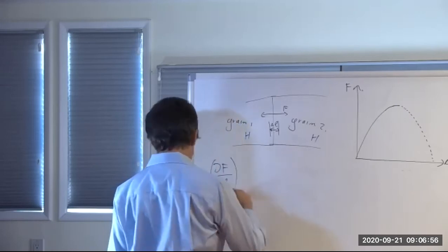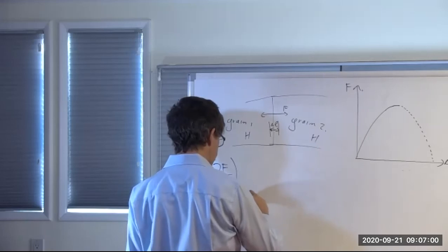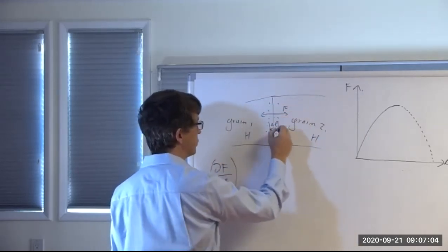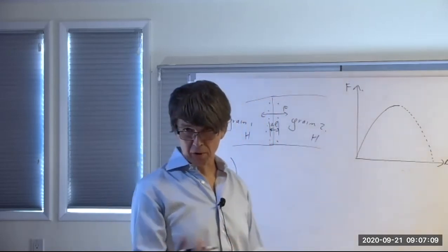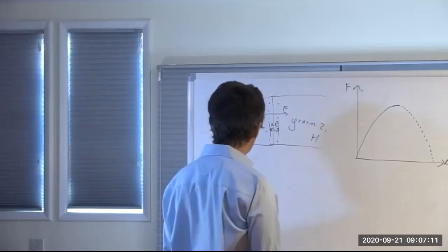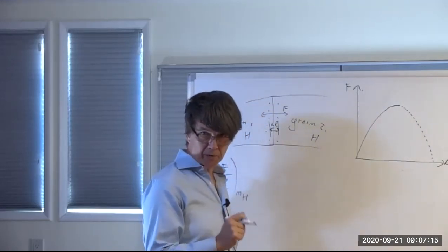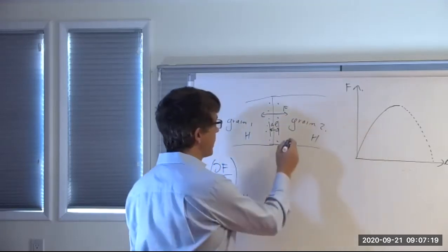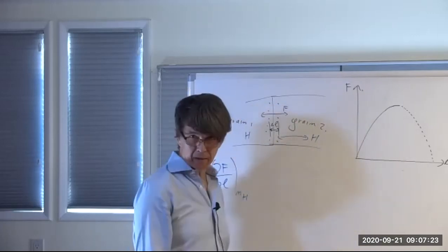At the boundary, I could derive it under constant amount of hydrogen. So, hydrogen segregates to this boundary to some extent. And there's a whole debate whether that makes it stronger or weaker. That's not the point now. But if I do this slowly, that's not the correct derivative, because if I do this slowly, then hydrogen equilibrates with the boundary at any position of L.